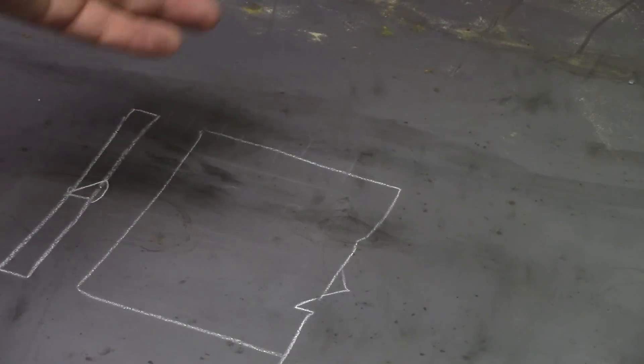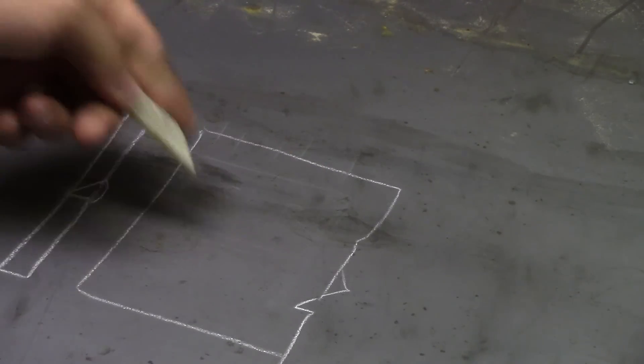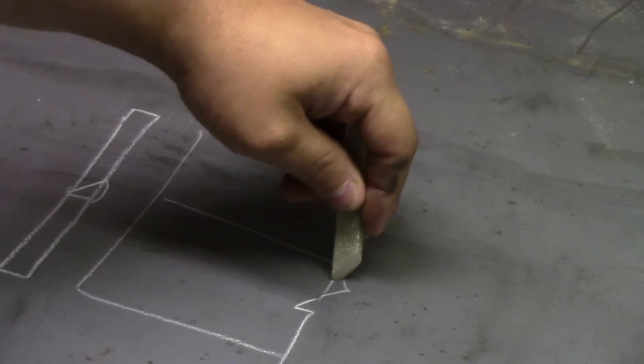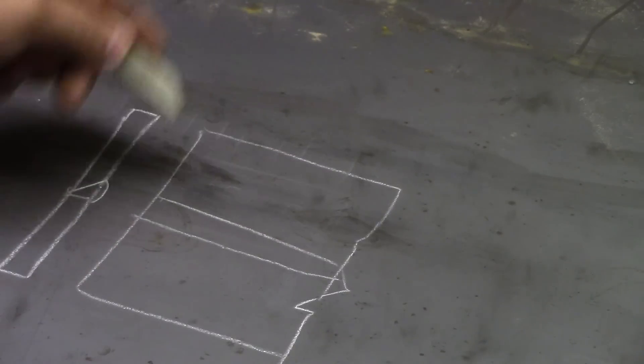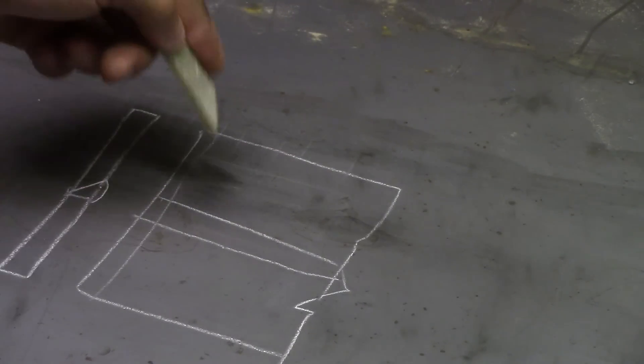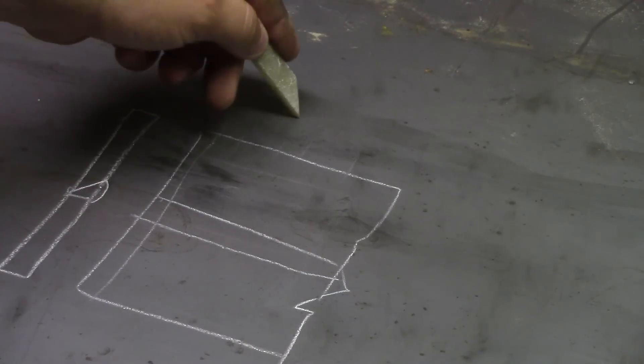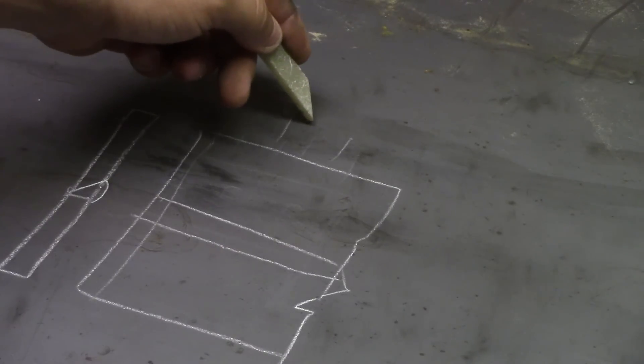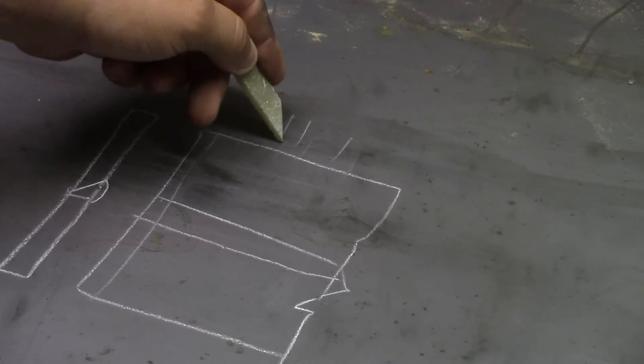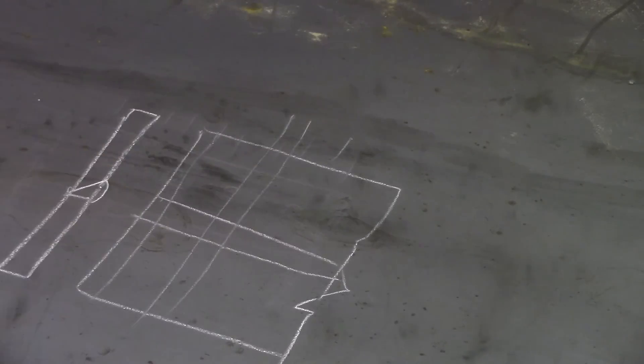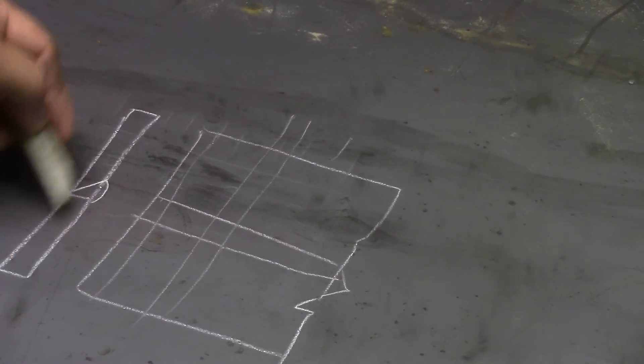If this is greater than three-eighths inch thick, you'll have this option. Even on three-eighths you normally have the option of doing four side bends rather than your two face and two root. In your weld, they still discard these ends, but instead of taking a one and a half inch wide piece, they're cutting three-eighths pieces out of it.